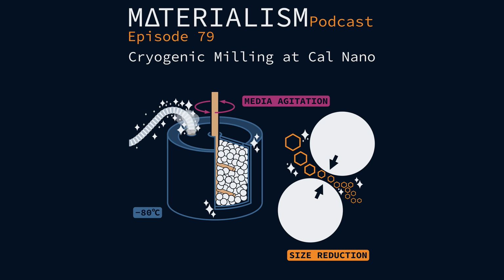We had this happen to us again on the high entropy alloy project, which might have been the first time that we met Eric. We needed somebody to help us mill this, and having heard about cryomilling, we reached out to Eric, and lo and behold, this technique was fantastic. It was able to take a 5-component and sometimes more mixture of transition metals, and even though some of those are ductile, some are not, it was able to mix them really nicely using cryomilling. So what's the magic of this? What's actually going on there?